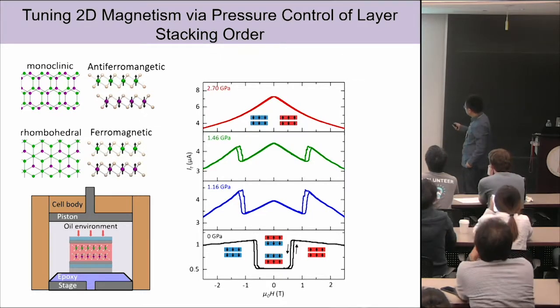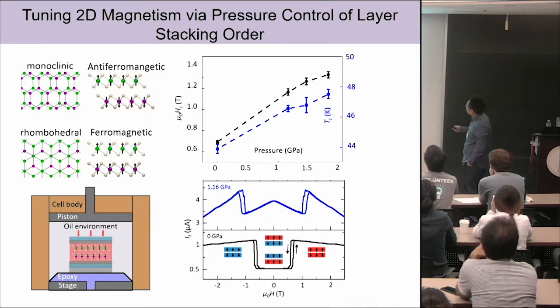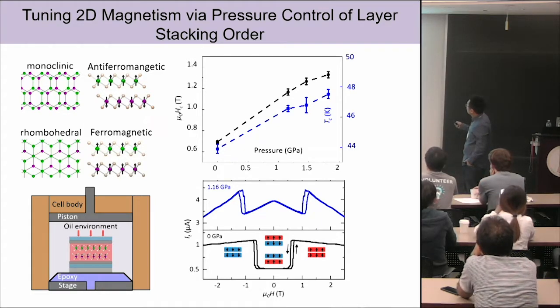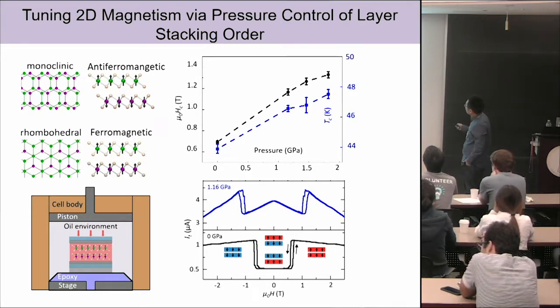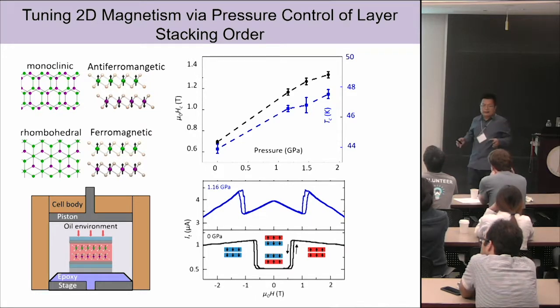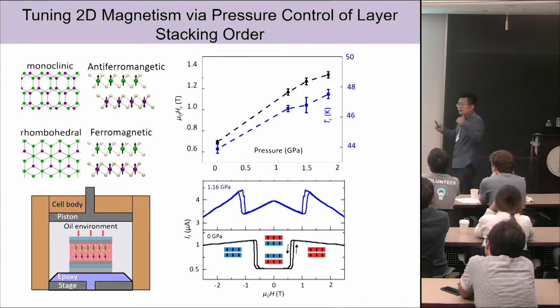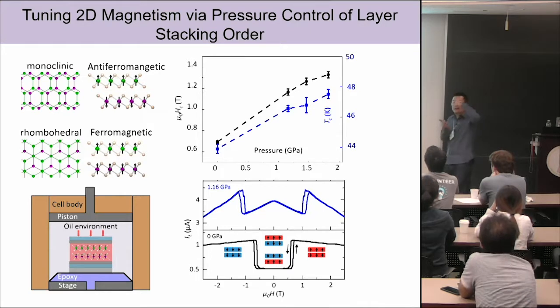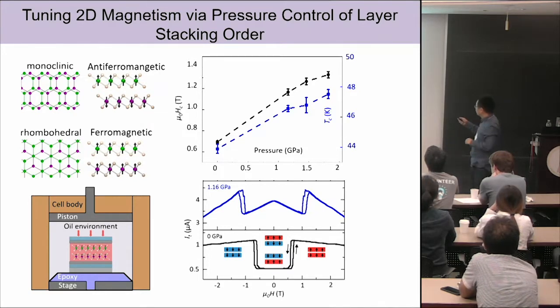The blue one represents the critical temperature for magnetic order to form, but you can see the critical temperature doesn't increase much, only from 44 Kelvin to about 47 Kelvin. This is small. And this also makes sense because the critical temperature is actually determined by intralayer exchange interactions, but the intralayer exchange interaction doesn't really depend on interlayer coupling, right? So all the results make sense.